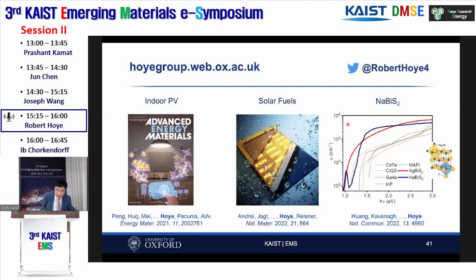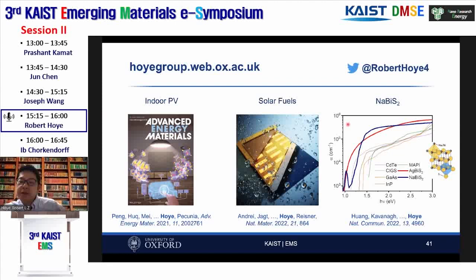Are there size effects? So we haven't found there to be size effects. We can tune the size through the synthesis temperature, from 4 nanometers to 15 nanometers or larger. And we haven't seen a significant change in the optical band gap.